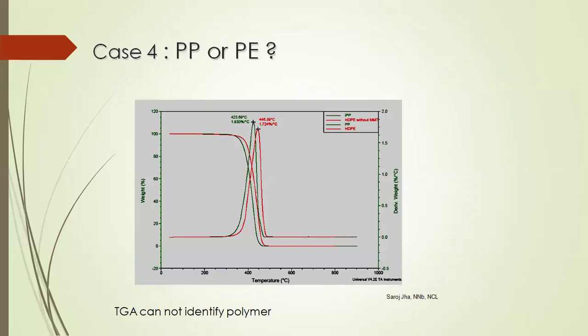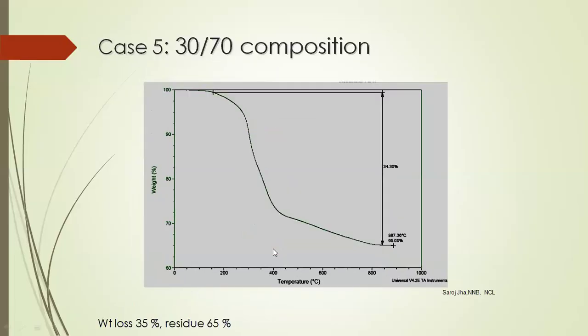Now, okay. The next question is, can I find out what my material is? Because I'm telling you that this is the first technique you can use on an unknown sample. So this is a TGA of PP and PE sample. If you see, onset of degradation almost similar. Residue, okay. If you see, degradation completion almost similar. So I cannot find out using TGA whether my material is PP or PE. You cannot identify what material it is. You can identify only onset and completion. Just remember, we will use it in the same slide in DSC.